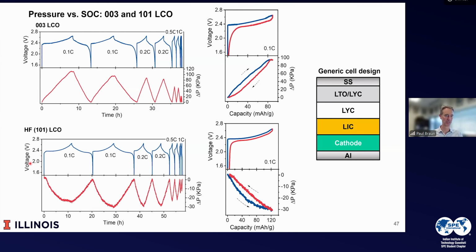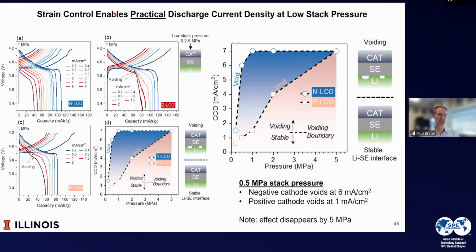So this matches the stresses on the anode and the cathode. Here, they're going to pull themselves apart. And so that shows up during discharge as voiding. And so if we make a battery with a very low stack pressure, so we don't push it together very hard, what you see is as you discharge, if the stresses are opposing, you have voids. On the other hand, when the stresses are complementary, voiding is prevented.